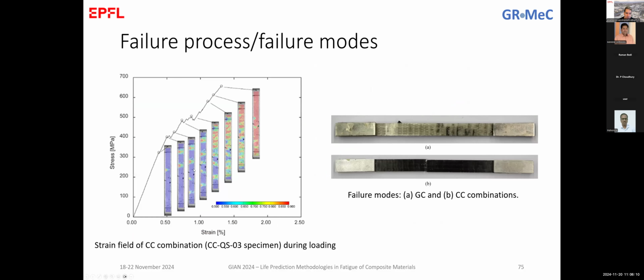So these are the strain field measurements that we could get with the DIC during the loading, and we can clearly see the damage that is initiating and propagating in several locations. What is obvious here, this localized damage, is the damage of the glass fibers. If I go to this specimen here, it's this part of the damage. So this is actually the bonding between the glass and the carbon fibers, and the eventual failure of the glass fiber layer. Do not forget that here we talk about unidirectional materials. The fibers are always along the loading direction.